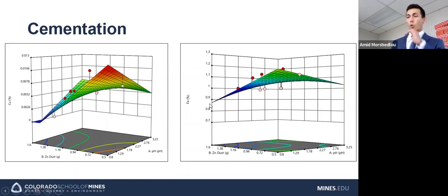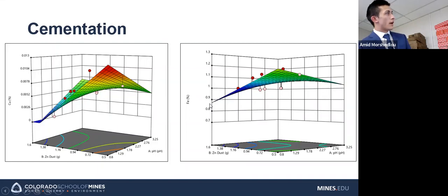And so what we can see in the case of copper is as we increase the amount of zinc dust that we add, we drop more and more copper out of solution. This is pretty much what we expect. And with pH, we can see that as we increase the pH and keep the zinc dust low, we'll get a drop. And the opposite occurs when we keep the zinc dust high.